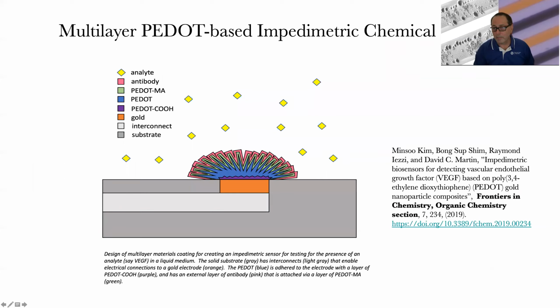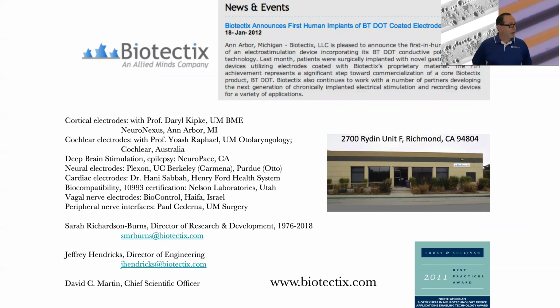This is just one example from our own group, looking at the use of these materials as chemical sensors, in this case for a growth factor protein called VEGF. That's very important for certain eye diseases. So this was done in collaboration with Raymond Iezzi at the Mayo Clinic, and we were able to get very sensitive detection of VEGF by using this system where we would measure changes in electrical current in the presence of the VEGF. So as you can imagine, there's a lot of commercial interest.